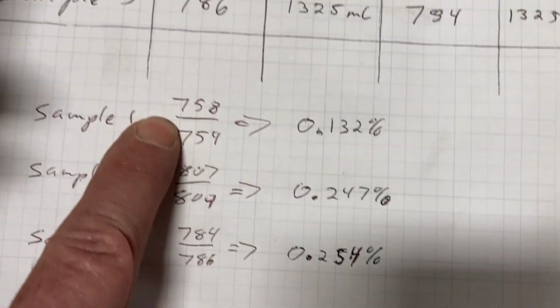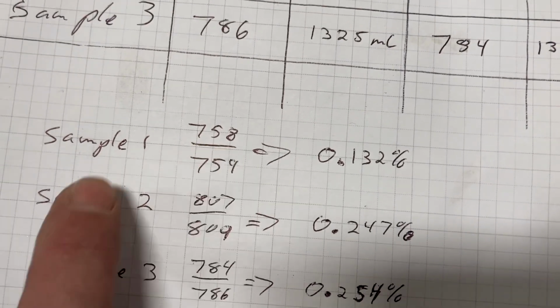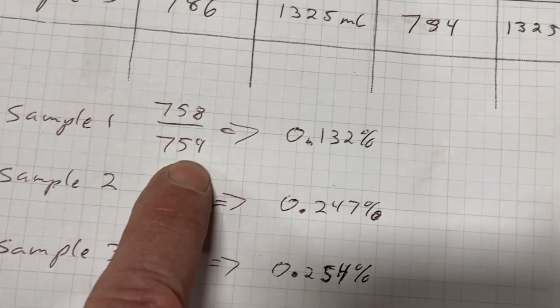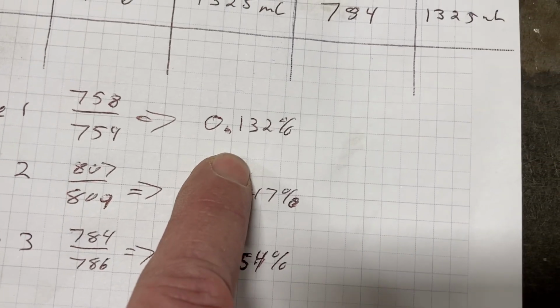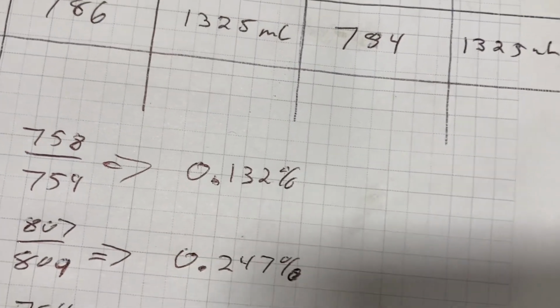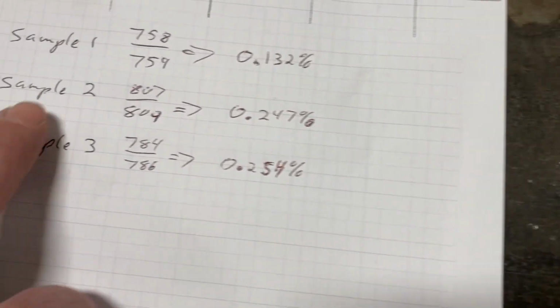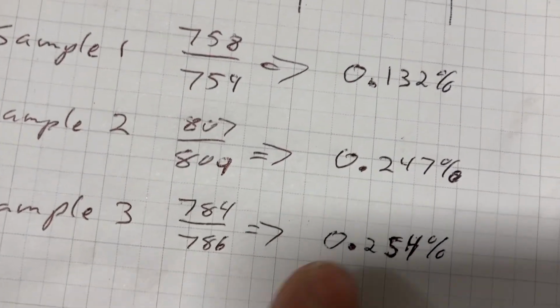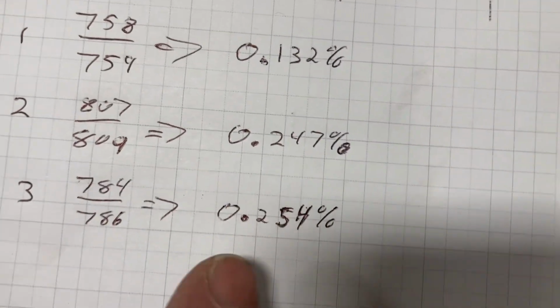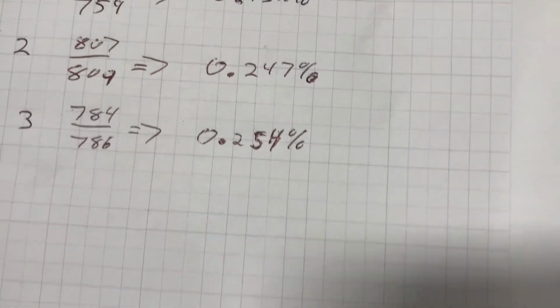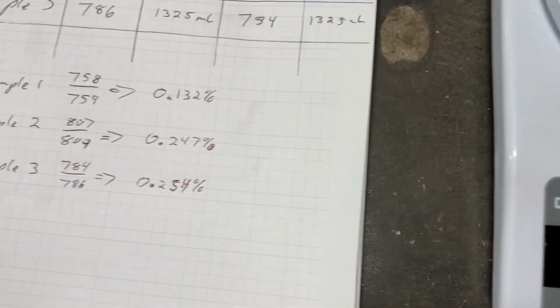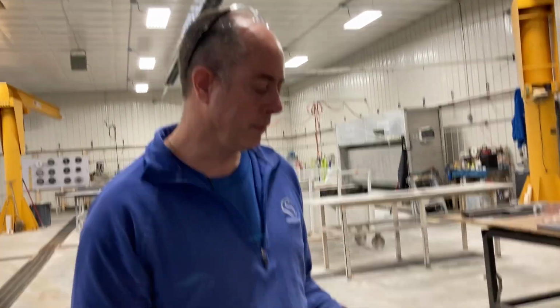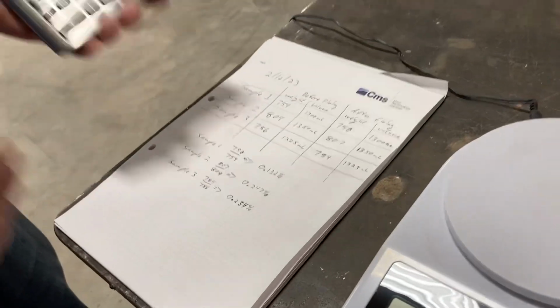So doing the math, sample number 1, 758 grams after we fired, 759 grams before we fired. So we get a difference of 0.132% resin in that sample. Samples 2 and 3, running the same calculations, we get approximately 0.25% resin. So if you average them all out, you're still gonna be pretty low percent. Definitely not the 1/3 of the stone that the customer was claiming. Statistically, way less than even 1% of the stone is resin.